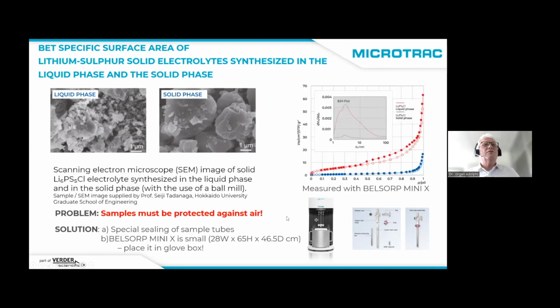So now the measurements are shown here. The isotherm, this is the adsorbed amount we find here for the y-axis, and this is the relative pressure. Then we see here the solid phase, this is the one on the right-hand side, and this is the isotherm of the electrolyte made from the liquid phase. And we also see a difference in the pore size here in the BJH plot.